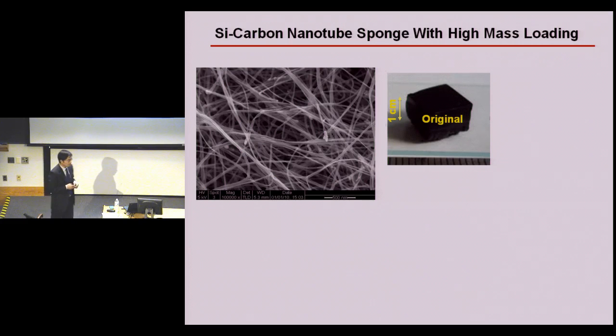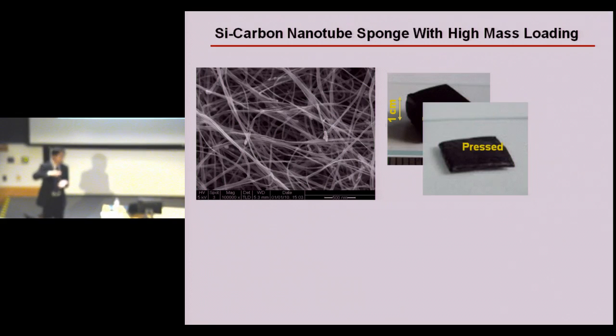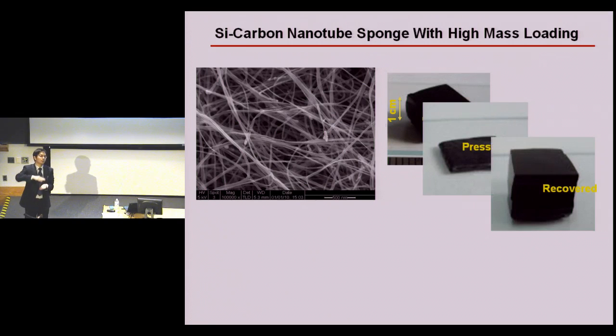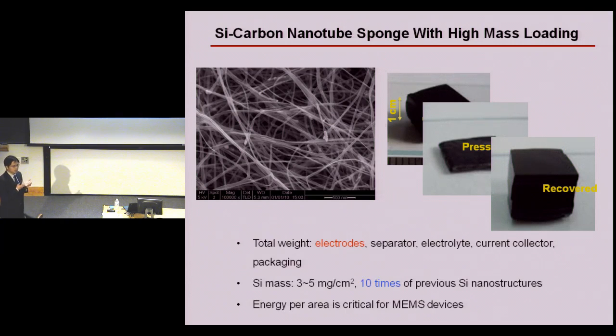So based on this concept, I fabricated a carbon nanotube film which I call a sponge. The reason is that this carbon nanotube film is highly porous. I compress this film, and if I release it, it will bounce back. So this carbon nanotube sponge is highly porous. More than 90% of the volume is porous. That means if I want to deposit silicon onto the structure, I can deposit silicon into the entire carbon nanotube framework.